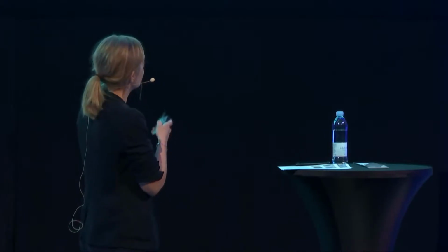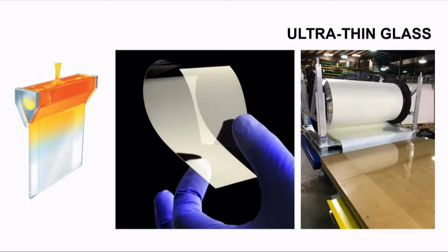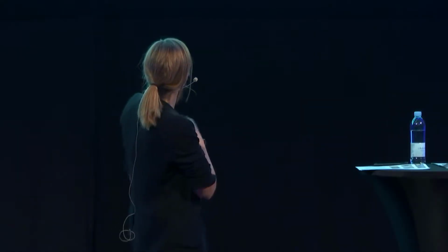It's then stretched and rolled into spools that go up to 300 meters in length and 1.2 meters wide. So imagine it, for a designer, 300 meters, that sounds unfathomable. That's like virtually infinite length of material. And it comes in variable thicknesses. Here we'll talk only about 0.1 millimeter, 100 micron, and 0.2 millimeters. You can have it thinner, you can have it thicker. We won't talk too much beyond those two boundaries. It's used for semiconductors, electrical wafers.